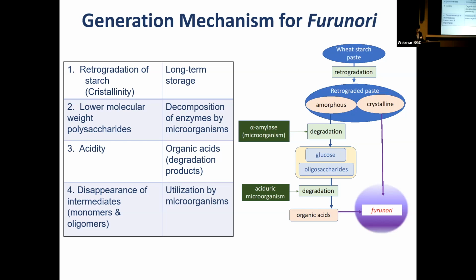the non-crystallized portion, is gradually decomposed by microorganisms into glucose and other saccharides, and finally into organic acids. This process begins at the top layer of the paste in the storage jar and then gradually works its way down to lower layers, taking approximately 10 years in all. Therefore, furunori is characterized by a crystalline structure and low molecular weight and acidity.